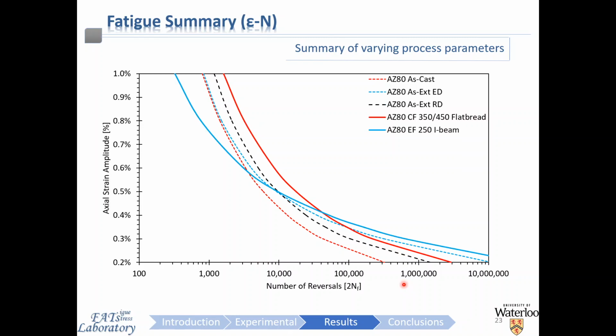Finally, we can introduce the optimum forge condition that illustrates a very dramatic improvement over all the conditions, especially in the high cycle regime at strain amplitudes less than 0.5, which once again is where we are desiring kind of high fatigue performance for this particular service loading. Finally, as a sanity check, benchmarking these responses against kind of the state-of-the-art material for these types of structural components, which is a 6082 T6 aluminum, we can observe that the forged material can meet or exceed kind of this baseline target for strain life behavior.